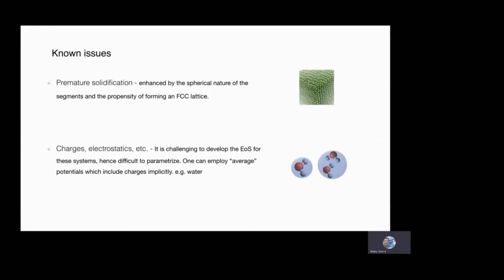I'd like to discuss also some issues that we know are happening with our model. Our model, of course, is not perfect by any means. There are two things that I'd like to point out as significant problems. One of them is the premature solidification, which is enhanced by the fact that our models, especially our homogeneous models, are made up of spheres of the same size. And this spherical nature of these segments, at very high pressures, has a propensity to form a solid. We have seen that this premature solidification affects us especially when we're talking about extremely high pressures, in the order of gigapascals. And there's nothing we can do at the moment for this. It's just a fact that there is a little bit too much symmetry in our model.